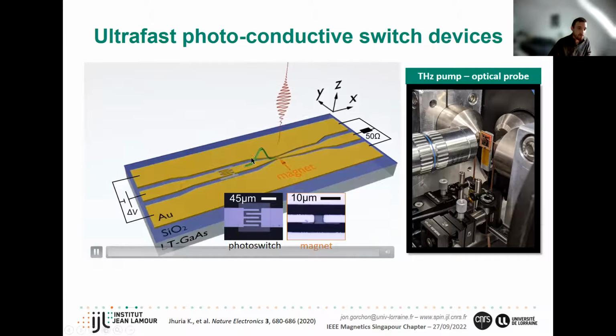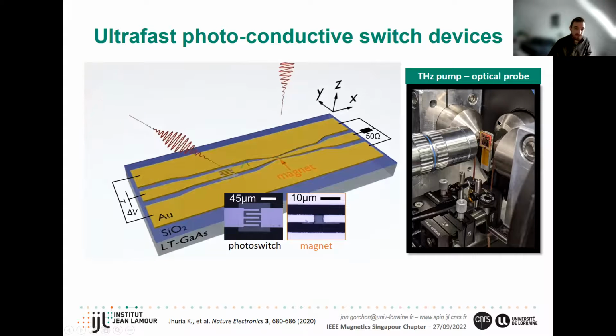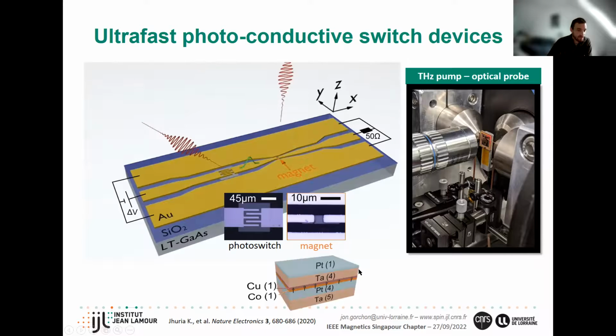So the way we do the experiments is like this: we pump the switch, we get this terahertz pulse going down the transmission line. It interacts with the magnet, and then we have another probe to look at the dynamics. And the setup looks like this. We have to use a microscope because this magnet is very small. We need to focus the probe there. We have electrical access, and we also have the out-of-plane field to saturate the magnet, but also the in-plane field to do spin-orbit torque experiments. So it's quite a complicated setup, I'd say.